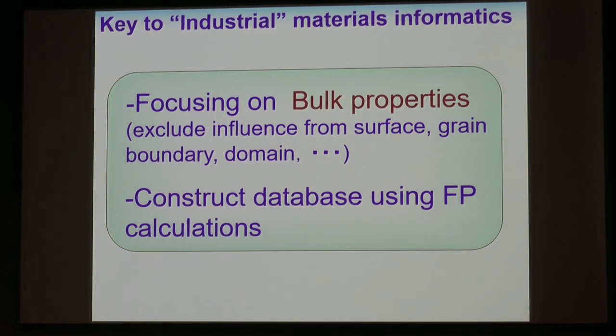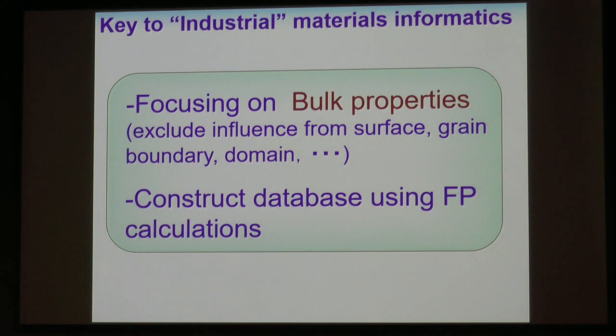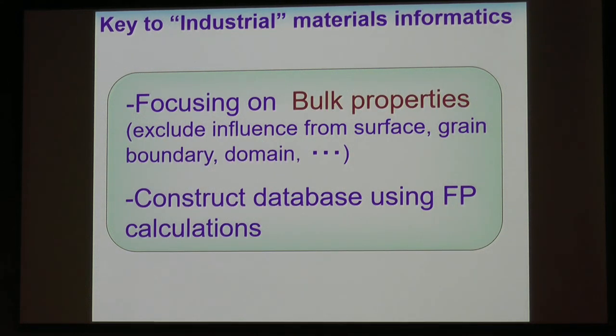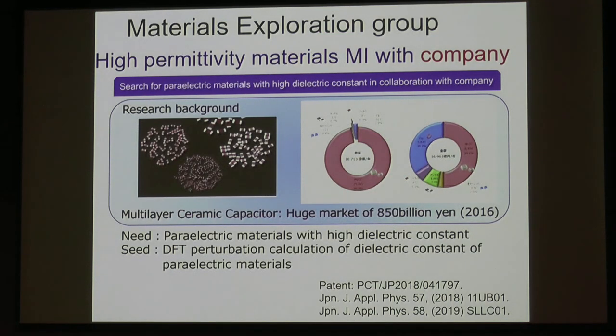So in this case, this is one solution key to materials informatics, to my understanding. Focusing on bulk properties. So to exclude effects from the surface and grain boundary or domain or something like that, then in this case we can calculate material properties using first principles calculations. So one example is as shown here. We're doing materials informatics for high dielectric constant materials in the paraelectric phase, not ferroelectric. So we collaborate with a private company. Then a company person submitted the patent and this literature.